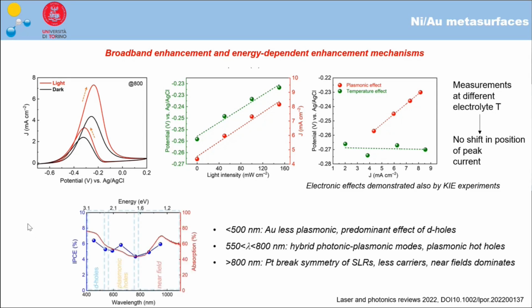And importantly, we can see that if we do wavelength dependent activity of our materials, we can enhance in a broadband manner the activity of these films, and the mechanism depends on the energy of the photons. So basically, we can have, for example, the interband transitions of the gold mainly working in the mechanism to enhance the oxidation when we use more energetic photons, or we can have only near fields mainly enhancing the reaction pathway when we use near infrared light.